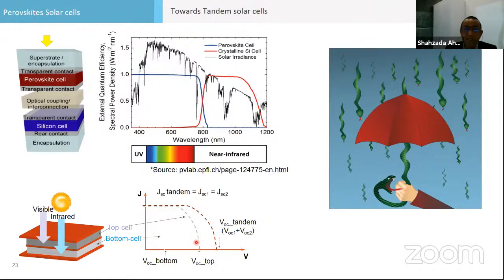Currently, 29.5% has been reported for silicon perovskite tandem, and the maximum for silicon in the lab is 25%. There are companies already working very actively on that. But for me, it also looks like a double-edged sword, because currently silicon has a lifetime warranty of 25 years, which we don't have for perovskite. So this is a big trade-off right now.